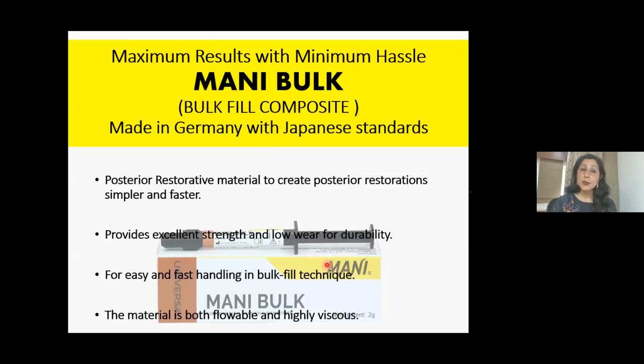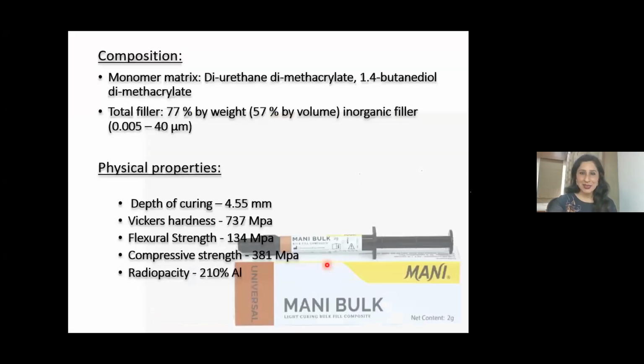So this Mani Bulk is a posterior restorative material to make posterior restorations simpler and faster. It provides excellent strength and low wear for easy and fast handling in bulk fill techniques, and this is both flowable as well as viscous, just like the Flow V. But what is the difference? The differences are many. First of all, the depth of cure is 4.5 millimeters, so you can take it in an increment of 4 millimeters. That is why this makes your life simple: you can just take a 4 millimeter increment and cure it. And if you want, you can top it up with a nano composite or a microhybrid, whichever you feel like, to give the color of the restoration, while the bulk is given by Mani Bulk.